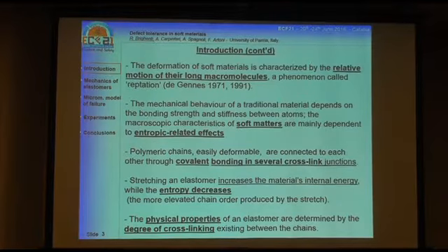We have to take into account that all these long molecules, as I show later, are linked together by means of covalent cross-link junctions, and that by stretching this material, we have an increase of the mechanical internal energy, and at the same time a decrease of the entropy because of the more order that we give to the structure.